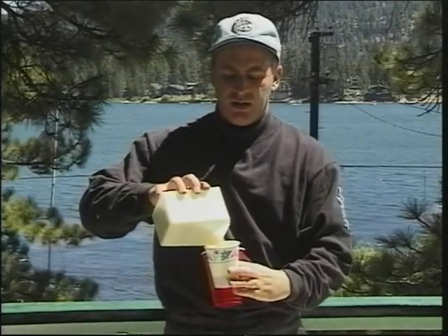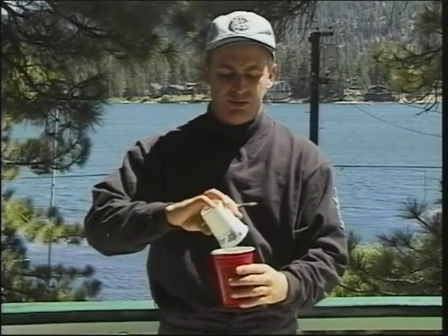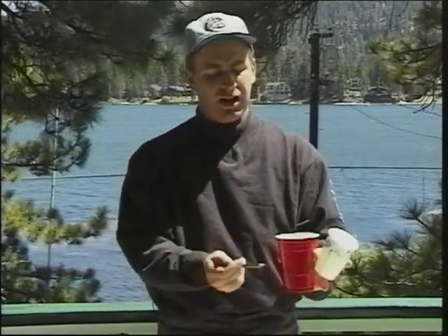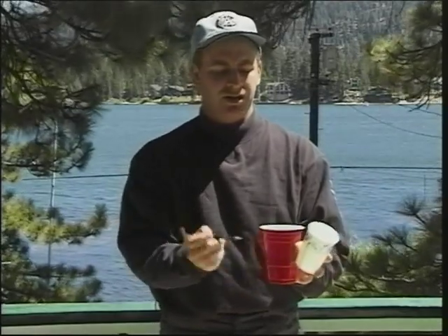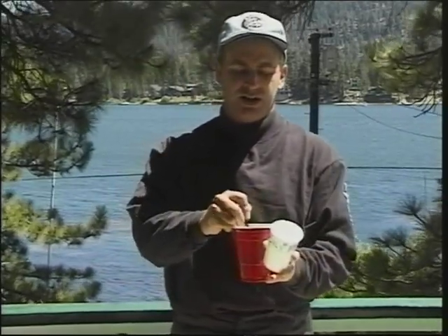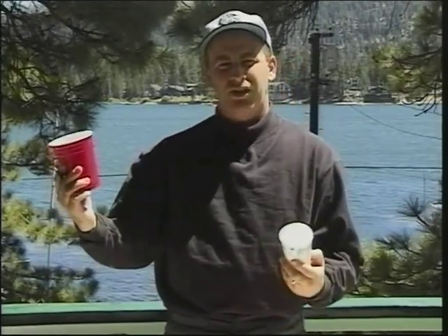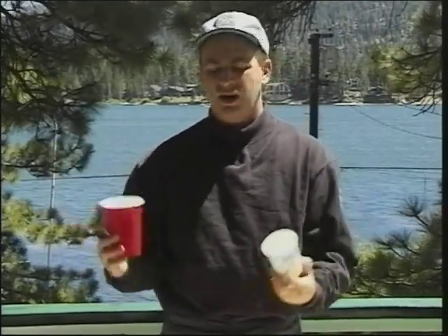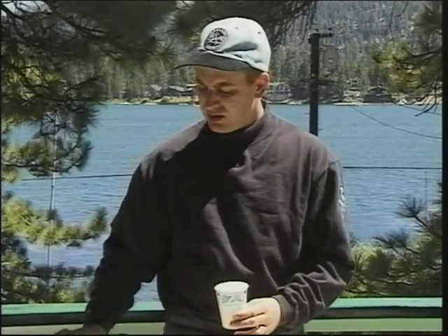And do it again. What I'm doing here is a 3-to-1 mix ratio. That's fairly common among most of the epoxy manufacturers out there. But now that I've got 3 parts from the small cup into the large cup, I make a mark on the large cup, and now I've got a mix: 3 parts of resin to 1 part of hardener. And this is generally accurate enough to get good performance out of any of the epoxies.